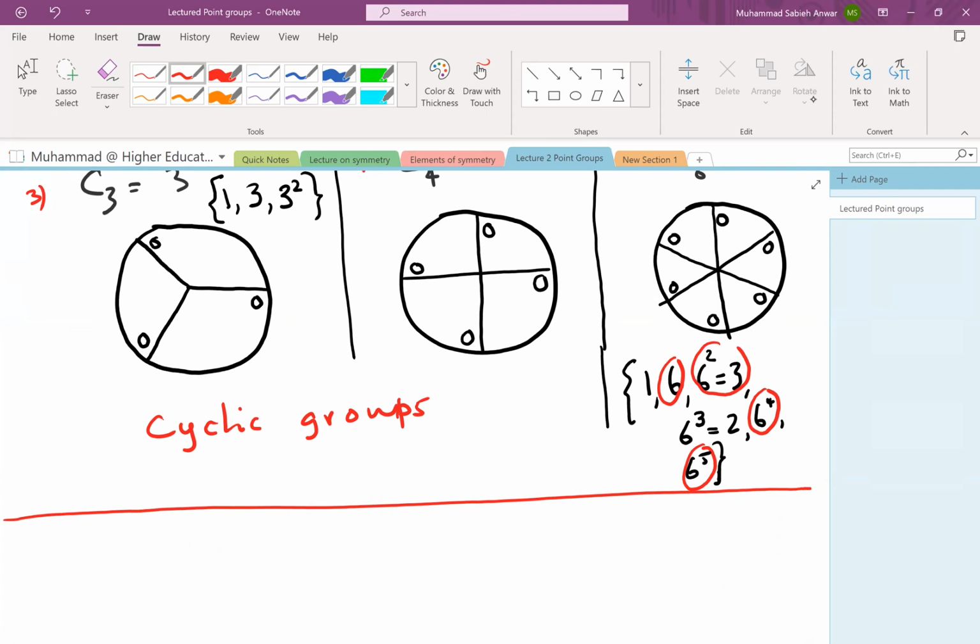So we can have groups with rotations. More than the sixth one, can't we go to infinite? Oh, no, sorry. In 3 dimensions, when you have finite points, discrete atoms on a 3-dimensional network, these are the only 5 cyclicities that you can have. You cannot have, for example, a 5-fold rotation or a 7-fold rotation. With these symmetry elements, you cannot completely fill up space, and there's a proof for that.